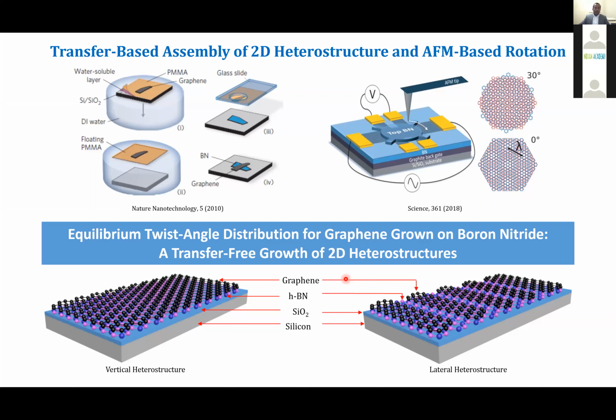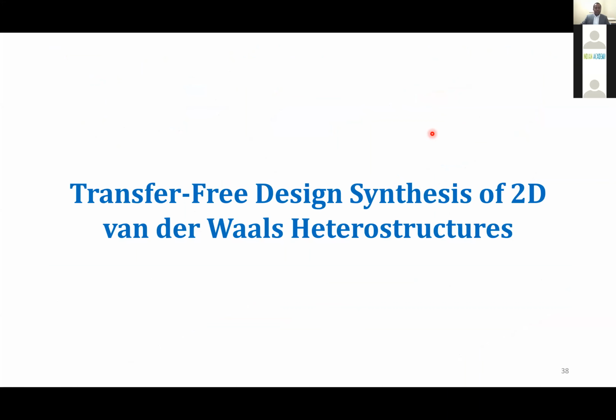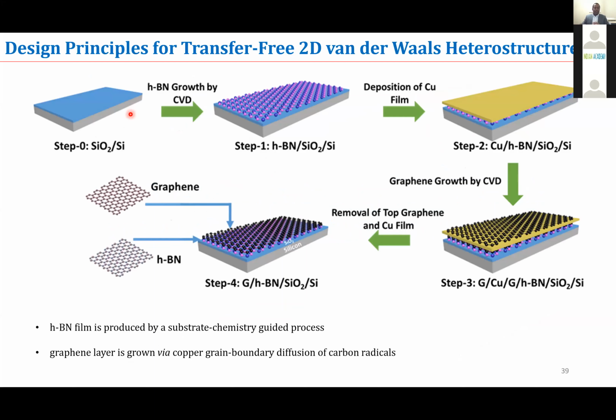However, again, we are using the same transfer-related steps, as well as an approach which is time consuming, and it is also difficult to precisely control the angle. So here is one study from our research, where we can create 2D van der Waals heterostructures without using any transfer-related steps. So what we can do is start with a silicon oxide substrate, and then grow hexagonal boron nitride first, and I showed how hexagonal boron nitride can be grown on a silicon oxide substrate at a high temperature using ammonia borane as the precursor.